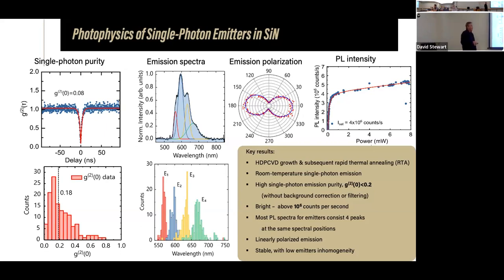And they all group around these 4 lines. When you go from one emitter to another, you always have these 4 overlapping lines, which means that the physical nature of these emitters is one and the same. It's broad, but it's one and the same type of emitters.